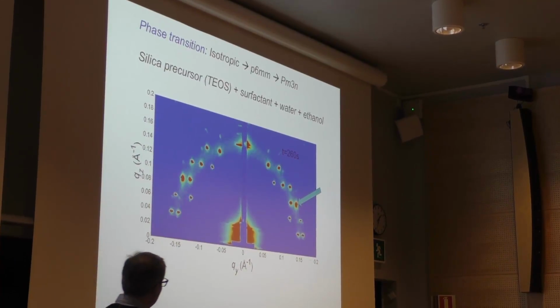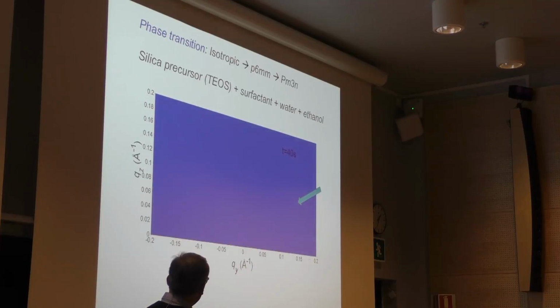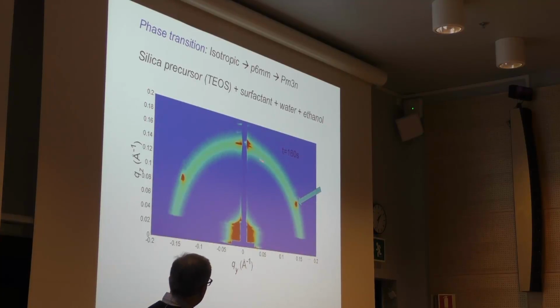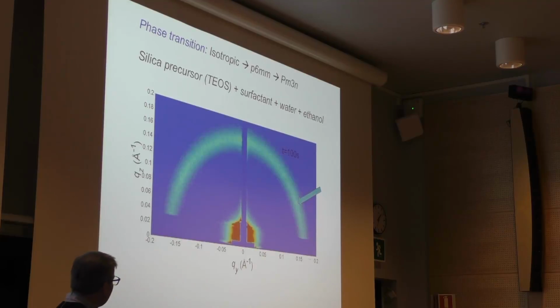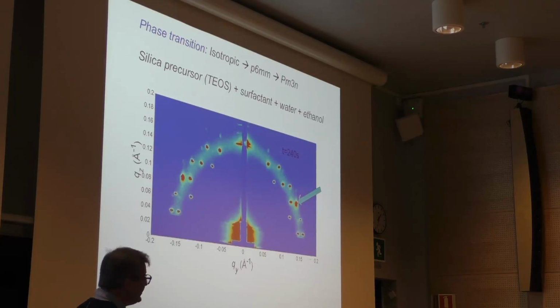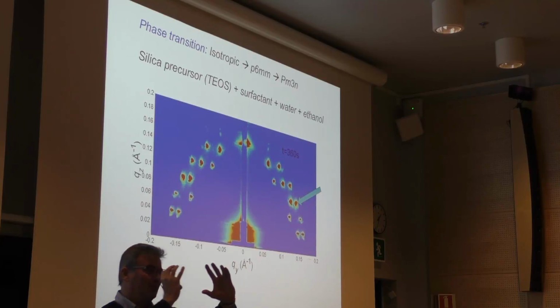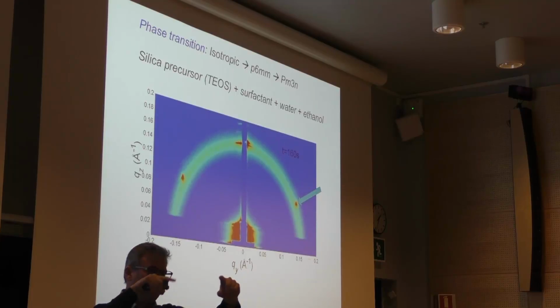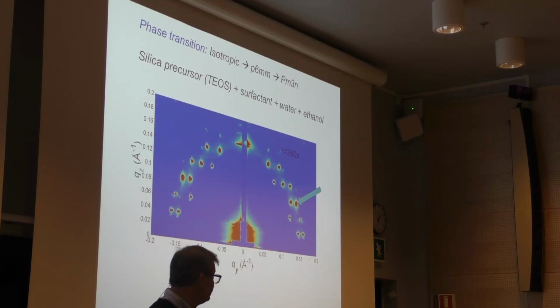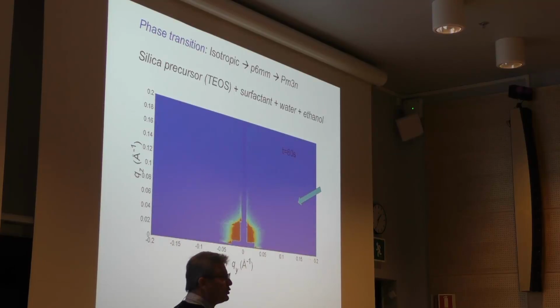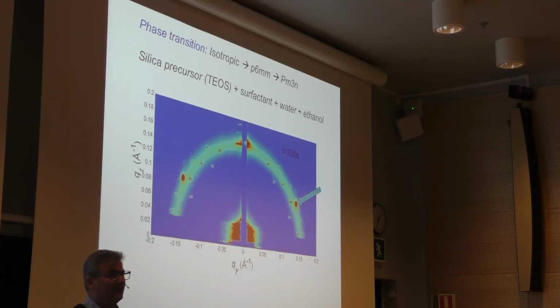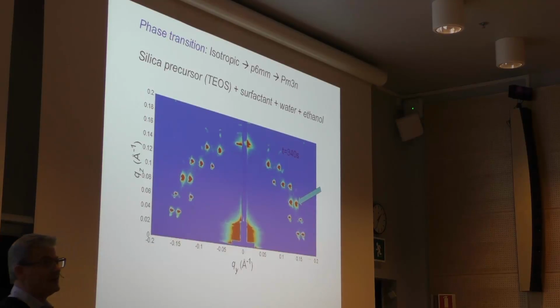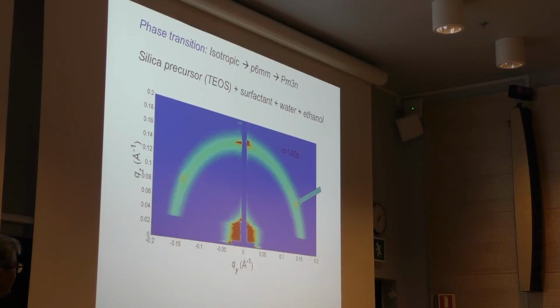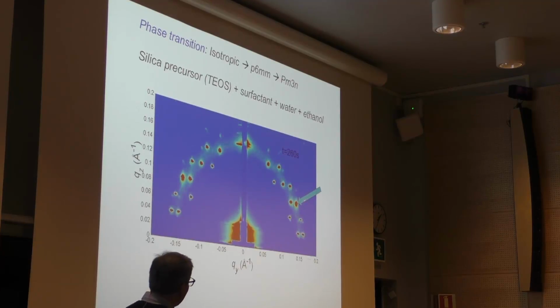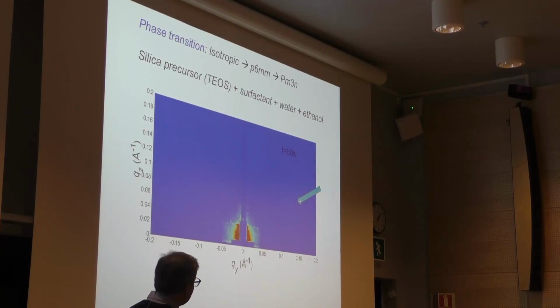So at the start, you see that there is no signal. Then suddenly, when this ring appears, this means that we have passed the critical micelle concentration. And then eventually you see something forming here. This is the signature of hexagonal tubuli of micelles forming inside of this solution. And you can see that this gradually grows over into a structure which has a very highly developed three-dimensional diffraction pattern, right?